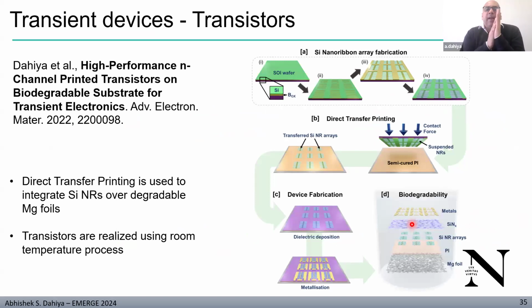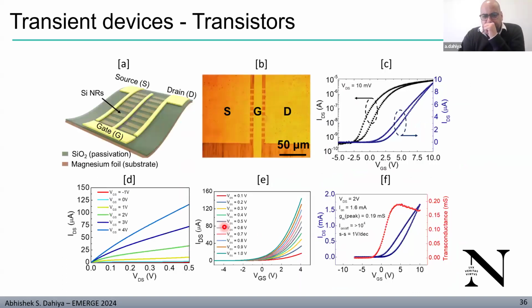This is the example where we have fabricated an N-channel transistor on biodegradable substrates, which is magnesium in this case. So we have used direct printing approach. We have this semi-cured polyimide and we bring a conformal contact to our fabricated ribbons, and this is how we transferred, as I mentioned earlier. And then a similar fabrication approach can be followed to fabricate these transistors. Interestingly, on such novel metal foils or substrates, performance-wise, it remains intact. We can reach as close as what I have shown on flexible devices.